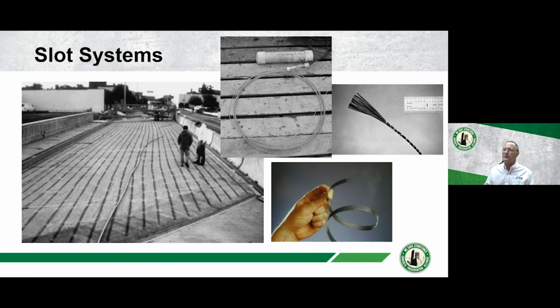So then they said, well, let's switch over and we do some slots. We can cut these slots with a saw, and then we can put a wire in there and we can fill it with a conductive grout, or we can use a graphite. This is a graphite conductor, and we can fill the slot with a grout, or then they used mixed metal oxide coated titanium. That's what this is down below. And this is a ribbon anode.